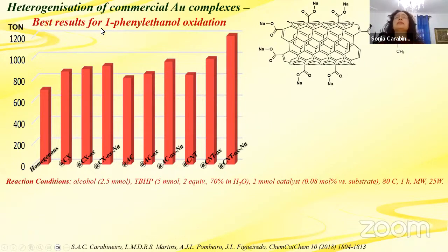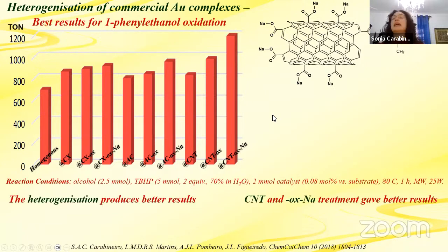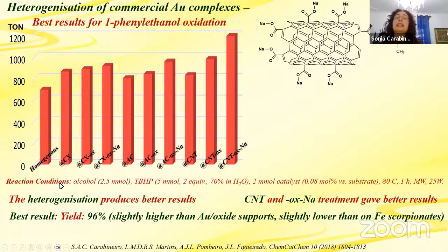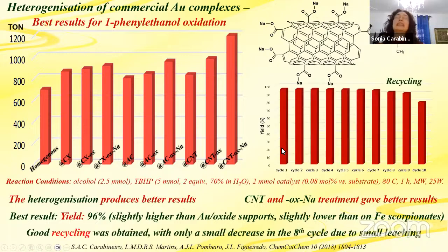Here we have the best results for 1-phenylethanol oxidation. So it was obtained with this complex, with phosphine. This was for the alcohol oxidation. And we have here homogeneous, and of course, when we heterogenize, it's better. And again, carbon nanotubes and this treatment give better results. The best yield was 96%, slightly higher than gold oxide supports, but slightly lower than on iron scorpionates, that was 98%. And again, recycling, we could recycle up to several cycles. But there is a small activity loss, of course, due to leaching after some cycles, after the 8th cycle.